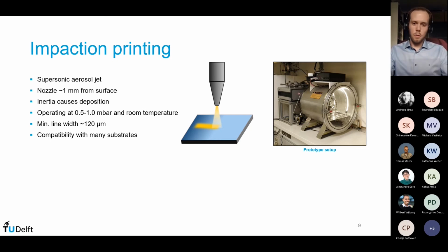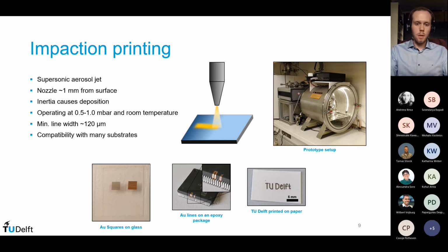Now, this last property is very useful if you want to print conducting lines, and is one of the reasons why you can use these lines immediately after printing. There's no curing or heating or anything other needed. The other benefit is that because it only is a 1 millibar vacuum, it's compatible with most materials that I've tried. So we've tried to print gold on glass. We have printed on microelectronic epoxy packaging, to see if you can do some additive manufacturing on top of that package. For example, print an antenna would be one fun application, or connect entirely different devices on it. We've also printed on paper, which works very simply.